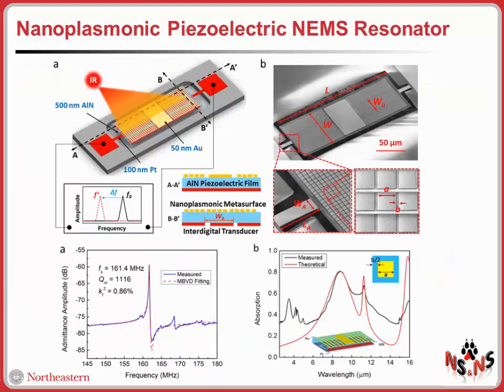So based on these ideas, we built the first prototype of a plasmonic piezoelectric nanomechanical resonator. So you see the device right here. Here is a cross-section of the device. The interdigital electrode is patterned on the bottom of the device, and that is used to excite a higher, in this case, a third-order contour-extensional mode of mechanical vibration in the plate, while the top metal layer is substantially two functional areas.